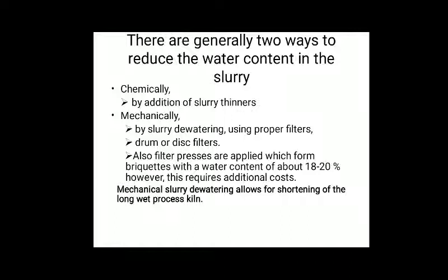And we are talking about the wet process here, because in the dry process there is no water involved. You do not need any dewatering. You just have to pre-dry it. But in the wet process, the slurry from the silos should be pumped into the rotary kiln, and it cannot be pumped in the form of slurry. Hence, dewatering of that slurry is done. The slurry is taken into a filter press or some press where the slurry is converted into cakes, and all the water is removed, and only 18 to 20% of moisture is allowed before the material enters into the rotary kiln.